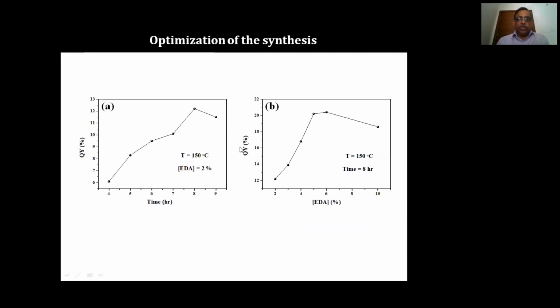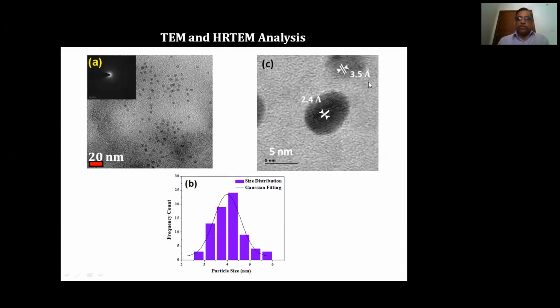So now look at the synthesis optimization. One can do a time optimization and a composition optimization. We have looked at the percentage of EDA used, and the duration of the synthesis. Once you optimize it, you go for the analysis, and the TEM analysis also gives me an opportunity to look at the size, somewhere around 4 to 5 nanometers for the carbon dot.